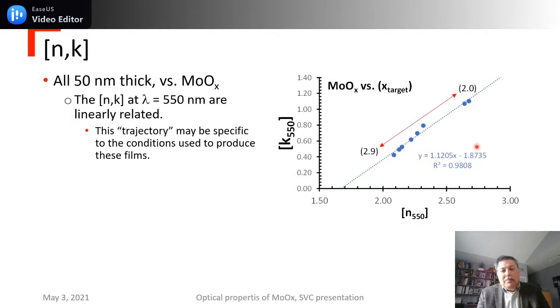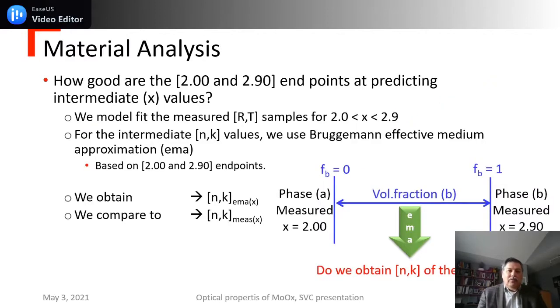I can imagine it might be possible that under different conditions, the data may not fall on this line. But in this case, we can see that there's a very high correlation to linearity, and this defines this material as it was made by sputtering. Now, what we're going to do is to say, okay, suppose I have a material that is made at a stoichiometry of, say, 2.6, and I have that measured data. Can I go to the endpoints, 2.0 and 2.9, and combine them in a method say, a Bruggeman effective medium approximation, EMA? And can I vary this dial between the 2.9 phase and the 2.0 phase? And can I recover the measured data of 2.6?